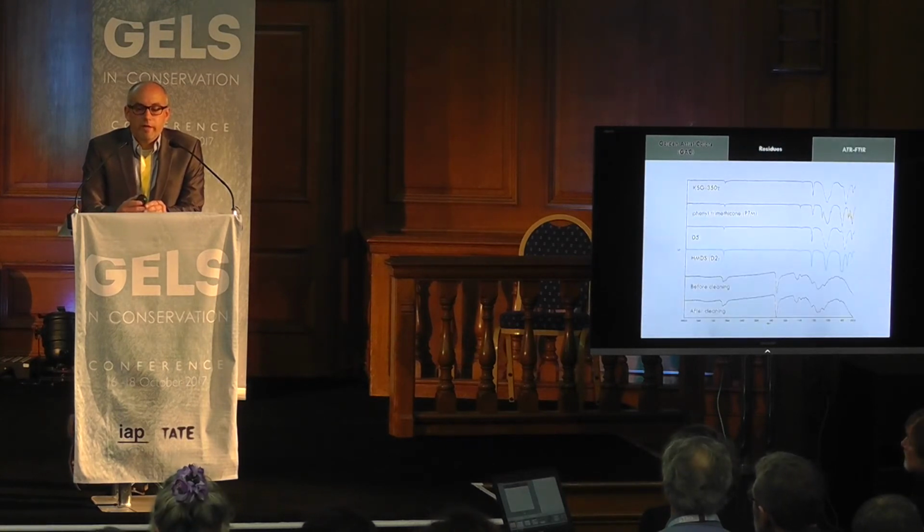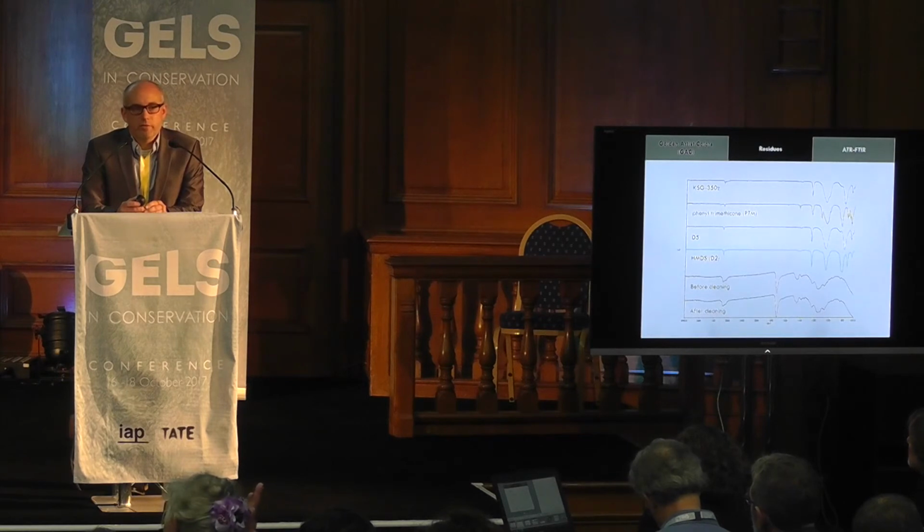When we look at residues by FTIR, we don't find residual silicone peaks before and after cleaning, so that gives us some credibility that we're removing silicone solvents from the surface of these paint films, removing particles, and the UV test as well could lend some further evidence.